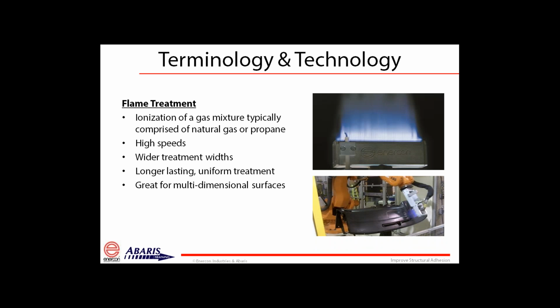Flame treatment is one of those that many people don't always associate with plasma, but it is one of those that we've put in our arsenal and tends to provide a very flexible application of a technology. Flame plasmas can be created with either natural gas or propane. They are very flexible in the fact that we can treat from about 1.5 inches wide on the small side to significantly larger. We probably make, in the range of 10 to 20 inch wide, typically 500 millimeter wide burners on the upper end. So we're able to create a very flexible technology in widths, but also when it comes to contours of parts.